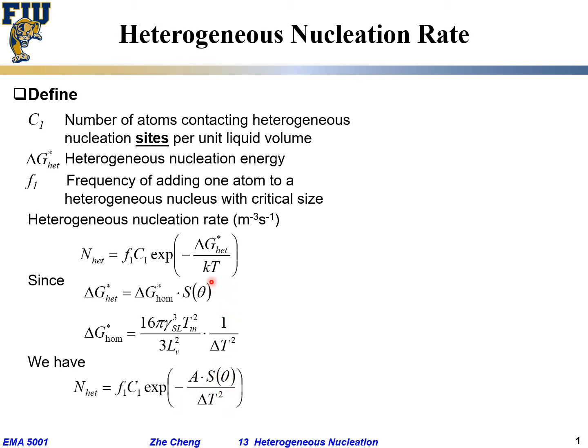You may ask what happens to this kT? That factor is much smaller than here, so we neglect the kT term here. We still have kT term here, but because the impact is much larger due to this ΔT, we kind of dropped it from here to here. You see we have a T term here.